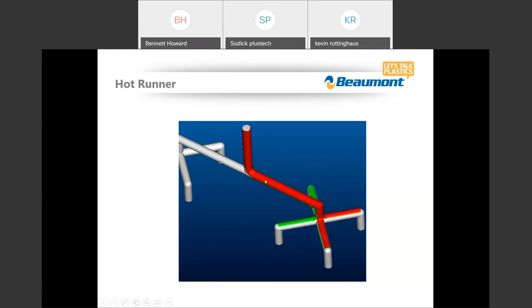So at this branch right here, we don't have an annular ring. We kind of have this half moon or crescent of higher shearing laminates biasing the top or A side of this runner. And those laminates are going to continue to come up to this turn, and they're going to stay within themselves. So they kind of, if you will, cascade or waterfall down on this side. And those laminates will develop on this side of the runner and the cooler laminates on this side of the runner. Now we end up with a situation where these cavities out here are receiving the higher shearing, less viscous laminates versus cooler, more viscous laminates in the center.